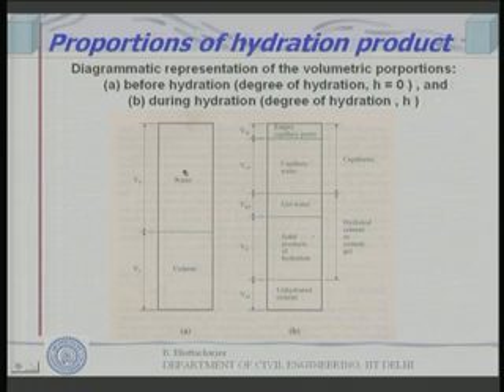So, this is schematically cement and water reacts to form some unhydrated cement, some solid products of hydration, some space that would be occupied by gel water, some will be occupied by capillary water, and there will be some empty capillaries. So, this total constitutes the capillaries, this total constitutes the hydrated product of cement or cement gel. This is inherent to this. Whenever this is there, this will be there because of the gelatinous structure. Since it is a gelatinous structure, it will have the interstitial pores and that would be occupied by water. We can do a little bit of calculation to find out what will be the possible volumes of all those ones, product of hydration.